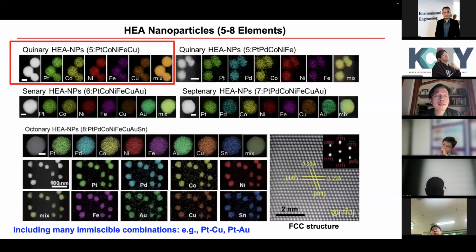So usually we need just one shock, okay? I just keep showing this so that you get an idea, but in our experiment, we just need one shock, right? What happened in this one shock? After the shock, you see all these homogeneous nanoparticles. And if you zoom in to see on the bottom right, you have this diffraction pattern, right? So you see these elements not only uniformly mixed, but also form a crystalline structure. So they form this FCC structure. And at the same time, the lattice site distribution, they are all random.